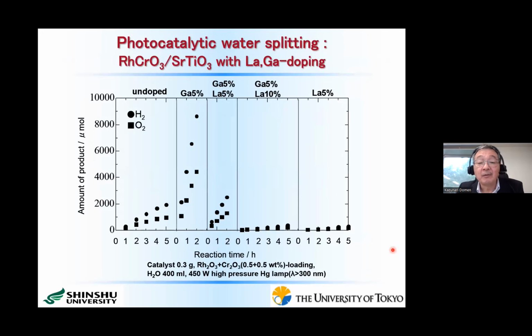However, if we measure the activity of the water splitting reaction by modifying only with rhodium and chromium mixed oxides, a very good hydrogen evolution co-catalyst, and in this case we don't use any co-catalyst for O2 evolution, we observe a very significant difference in activity. When we use stoichiometric strontium titanate, this is hydrogen, this is oxygen evolution, it evolves both hydrogen and oxygen in a 2:1 ratio. So this is the standard activity.